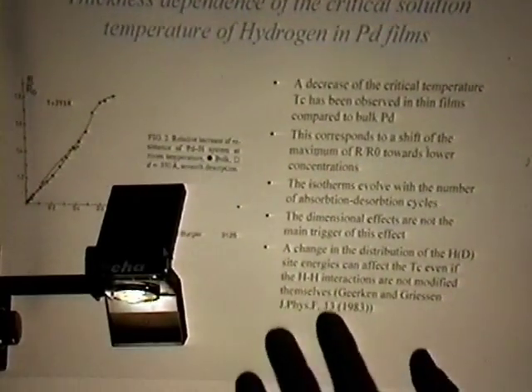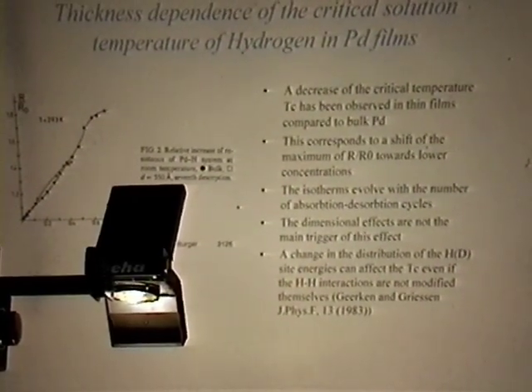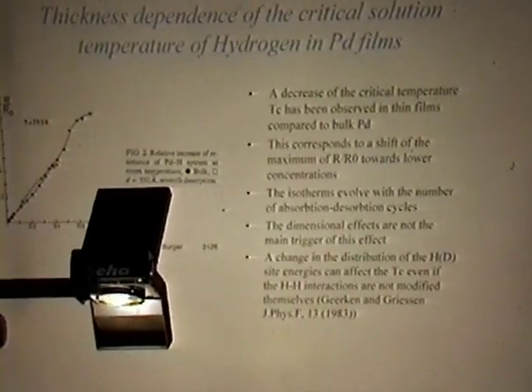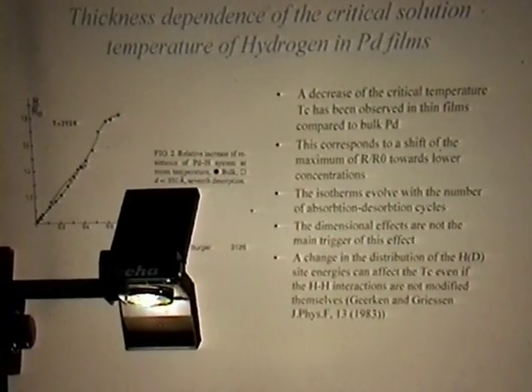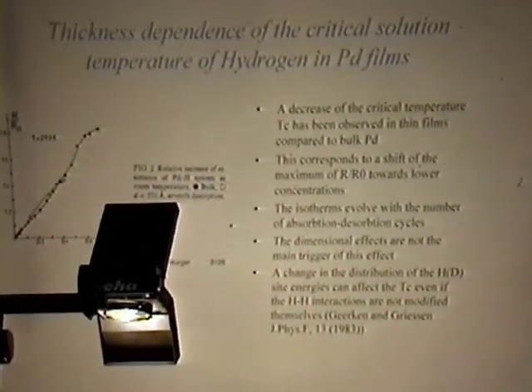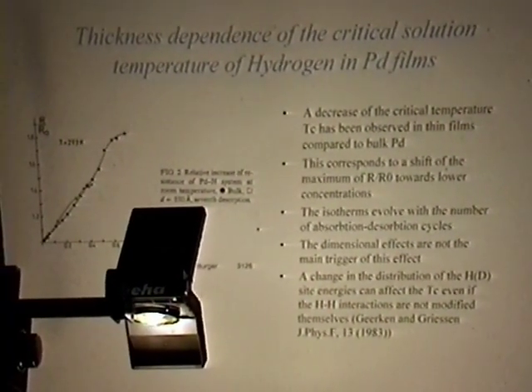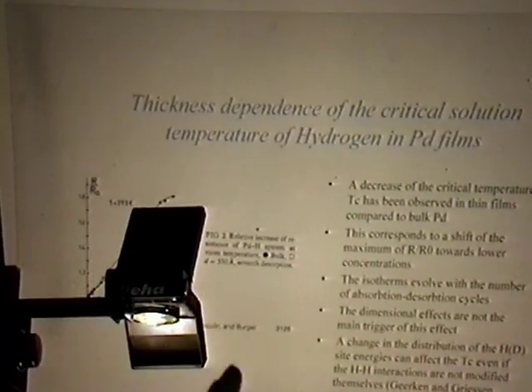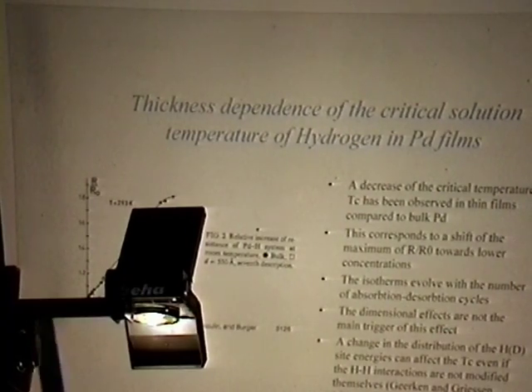But looking in literature, we found that it's well known that there is a thickness dependence of the critical solution temperature of hydrogen in palladium films. A decrease of the critical temperature of thin films compared to the bulk was measured, and I can give you the reference. This corresponds to a shift of the maximum of the Baranowski curves towards lower concentration. You can see it here in this graph.